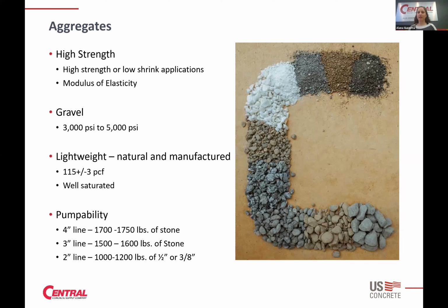There are also lightweight aggregates available for reducing the weight of a structure, reducing the weight of the concrete. There are different options available. A natural lightweight, which would be something like a pumice or a scoria, is going to have a lower embodied carbon than a manufactured lightweight. Manufactured lightweights are going to be things like expanded shale, expanded clay, and those are manufactured by going through a kiln process. So that's what gives them a higher embodied carbon. And what you have available in different markets is going to vary on your location and sources that you've got available close by. But those are conversations you can have with a ready mix supplier.